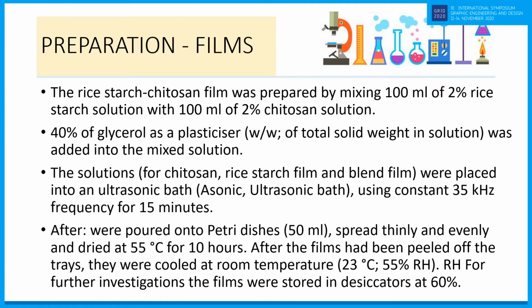After this treatment, the mixtures were poured onto petri dishes, spread thinly and evenly, and we dried them at 55 degrees Celsius for 10 hours. After that, the films were peeled off these petri dishes and cooled at room temperature.